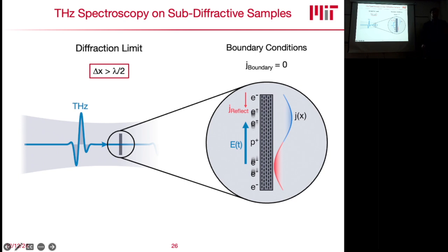And so this exemplifies the importance of these boundaries, provided that your scattering time in these materials is large enough, right? Your reflected electronic wave needs to be able to propagate through the whole sample to give rise to effects that you also feel in the center of the material. Otherwise, if the scattering is too small, you'll only see those effects at the edges. And so conventional terahertz spectroscopy cannot measure these things, because you're averaging over this whole sample. And if you average over this current pattern, you won't get anything, right? Current up, current down, averages to zero. So you can't measure this with conventional terahertz spectroscopy.